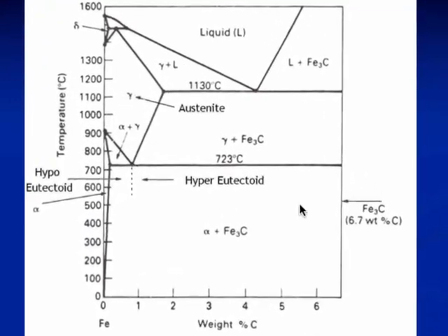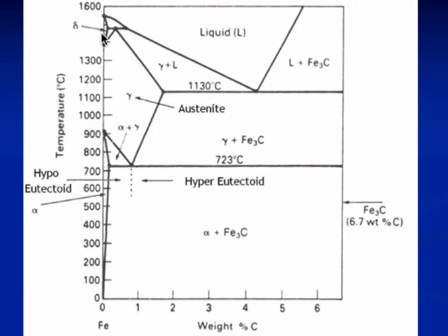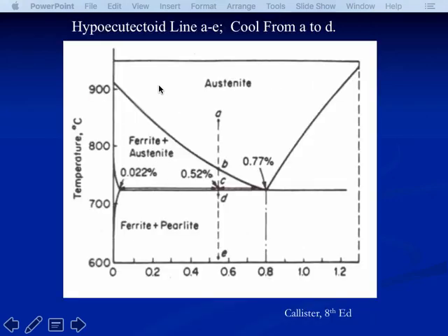There's a two-phase region and a single-phase region. There's also a single-phase region at high temperature called delta iron — body-centered cubic again, but of little commercial interest because it only exists at very high temperatures. If we take a sample in the austenite state and cool it slowly — remember, this is an equilibrium diagram, so we must cool really, really slowly — we hit the boundary of the ferrite and austenite region. So we begin to make ferrite, and as we cool through this region, we make progressively more and more ferrite.